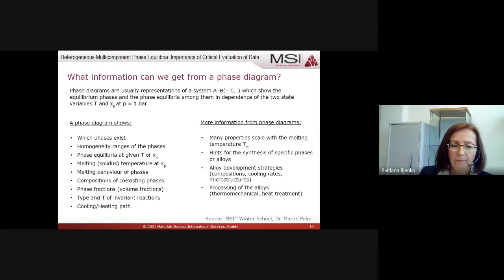Except for that, there is more information which one can get from the phase diagram, maybe not directly, but get some hints. Many properties, for example, scale with the melting temperature, or one can get hints on the synthesis of specific phases or specific particular alloys. And also hints on alloy development strategies: which composition should be selected, at which cooling rates it's better to prepare, what microstructure we will expect in this case. And of course, on processing of the alloys, selecting, for example, heat treatment conditions. This all can be read from the phase diagram.